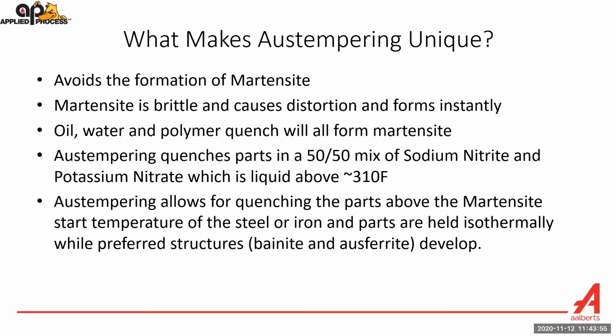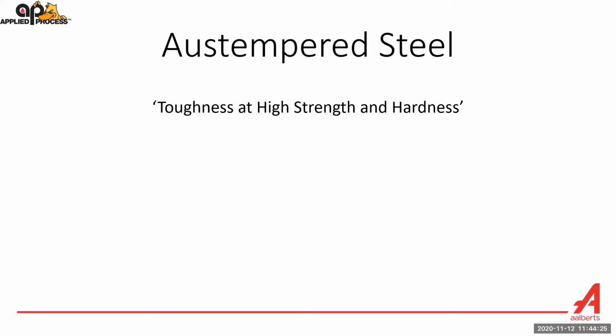If you think of how hot you can get water, it boils at 212 degrees Fahrenheit. Oil starts to become unstable above about 300 or 350. So relatively low temperatures in comparison to what we can get to with quenching in salt. And then austempering allows for quenching above what's called the martensite start temperature. And then we hold it there while this preferred microstructure called bainite in steel, or ausferrite in ductile iron, develops. So we're going to talk a little bit about austempered steel.